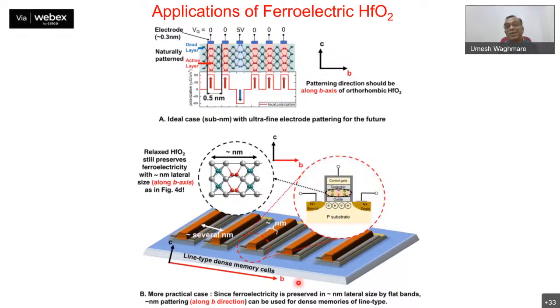And here is our theorist's imagination: the beauty of hafnium oxide is you don't need a technology to nano pattern it. Like in semiconductor memories, you need patterning of the active material at small scale. In hafnium oxide, it's not necessary because the 3D architecture of the crystal itself supports ferroelectricity at scale. So all you need is deposition of electrodes on a small enough length scale. If you can deposit electrodes and connect on half a nanometer, you will have the ultimately high density.